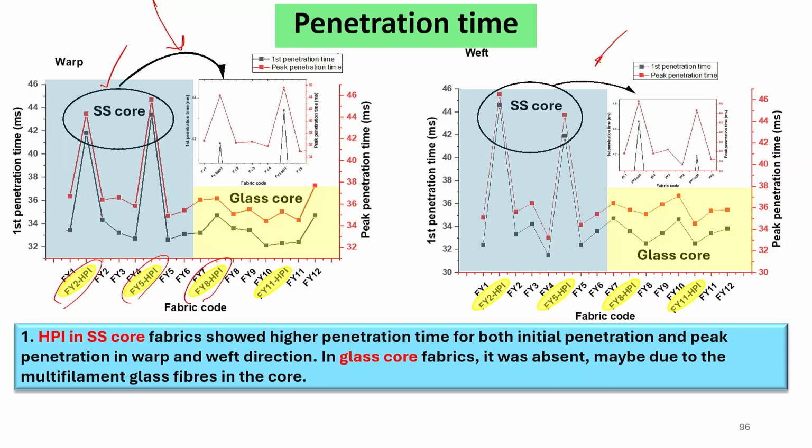The hard particle impregnated SS core fabric shows the highest penetration time for both initial penetration and peak penetration.